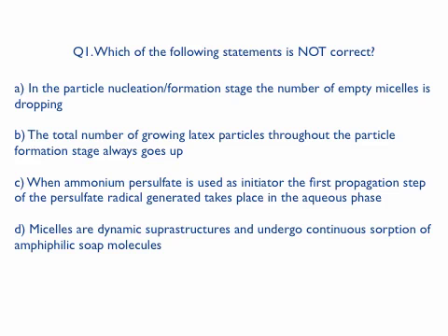This thing will swell up a little bit and take up more monomer. So the surface area of this blobby object becomes larger, but it only has one sulfate group. That starts to become colloidally unstable, and a bunch of these then group together in order to get a higher charge density with respect to surface. So the incorrect answer, and what we asked for, is answer B in this particular case.